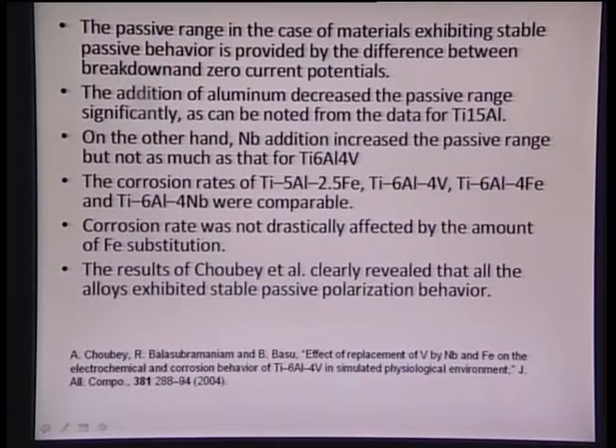And again, the passive regime in case of these materials: they exhibit a stable passive behavior between the zero current potential and the breakdown potential. So between this regime, they show a passive region, and we saw that the addition of aluminum basically decreases the passive range. So we had titanium 6 aluminum 4 vanadium. The addition of aluminum decreases the passive range, as we also saw for the titanium 15 aluminum alloy. But the niobium addition increased the passivation range,